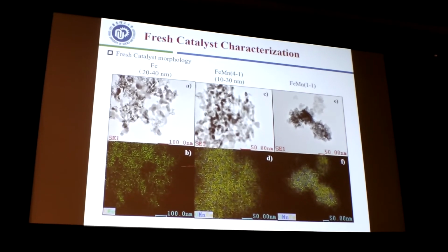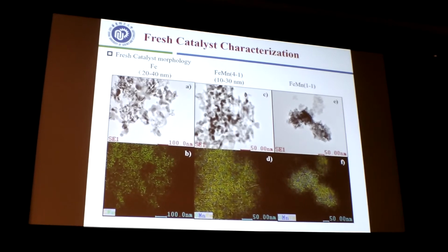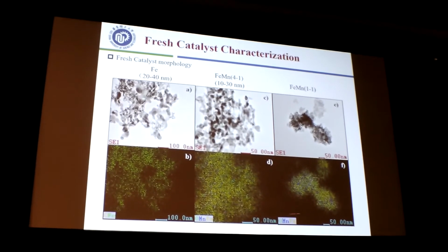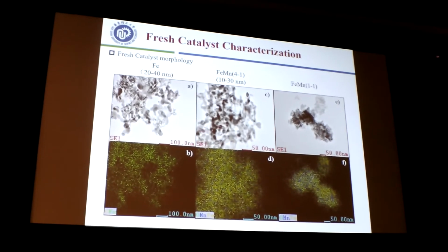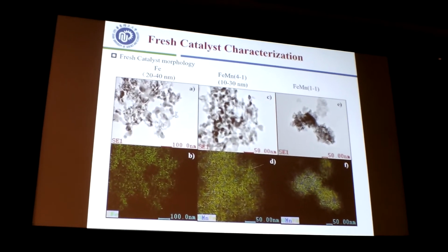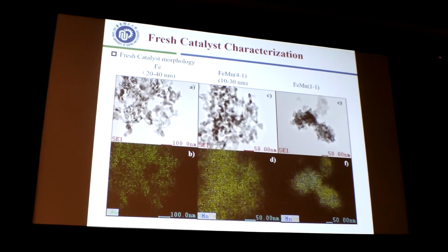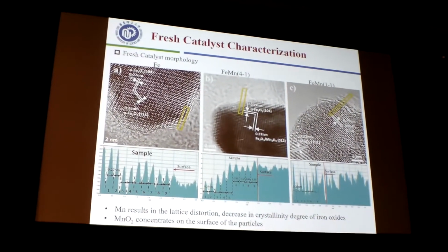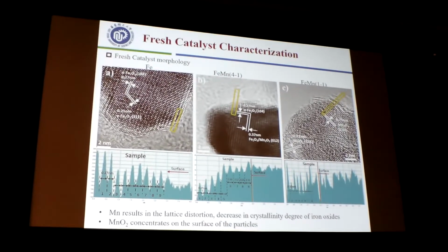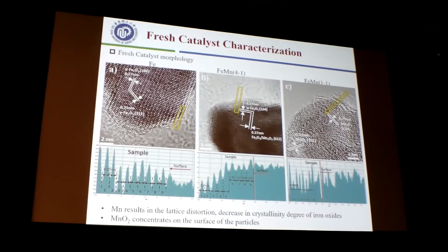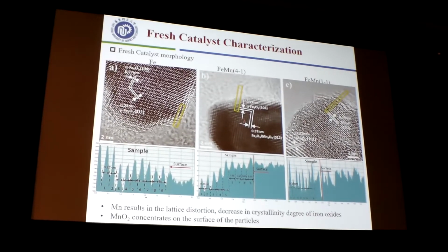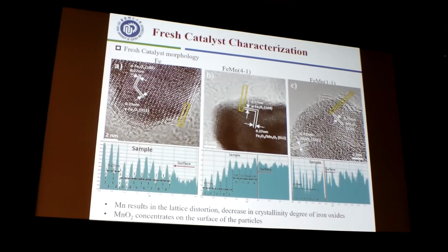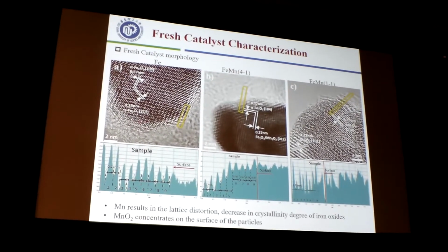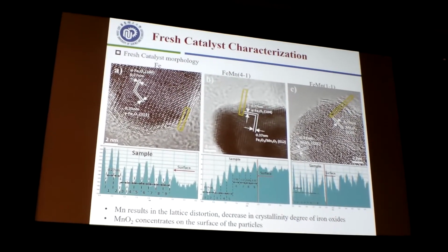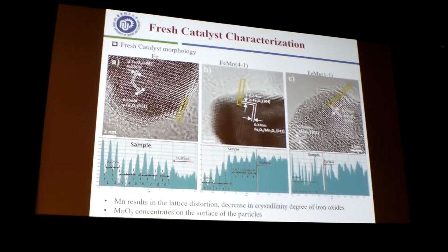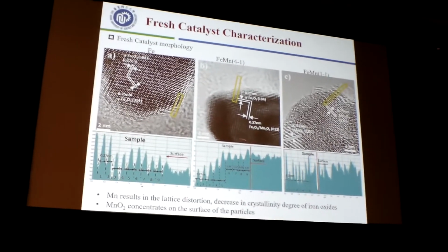So the figure down below shows the elemental mapping of the catalyst, which also shows that the iron, manganese, and the oxygen are evenly distributed in the catalyst surface. So here is the image of the HRTEM, and we can observe the lattice distance and lattice orientation of the prepared catalyst. So for the single iron, we observe the alpha and gamma iron oxides, which supports our findings in XRD. And for the iron manganese 4 to 1, we didn't observe the gamma distance.